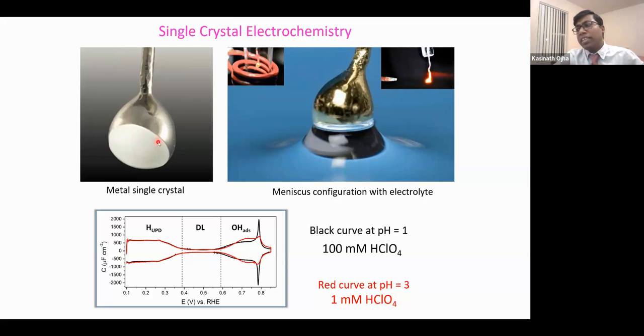I don't think I have something to show, but this one is a very typical signature electrochemistry. I call it a capacitance curve, or a cyclic voltammogram. This is very typical for platinum 111. If you have another facet, you won't get this one. If you have even a small degree of error, then you end up with two peaks over here and here. Those are hydrogen adsorption peaks at the step sites.